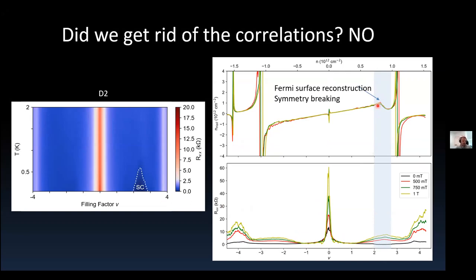The reasoning why we went with the metal gates is that if you have angle disorder, this roughly translates to a charge disorder, and it's easier to make these devices if you use metal gates. So until we figure out how to get rid of the angle disorder, there's not much reason to do the graphite gates. In STM experiments we do have a graphite gate, because in STM it's natural to have a graphite gate. But we will probably now try to make some devices with graphite gates as well.